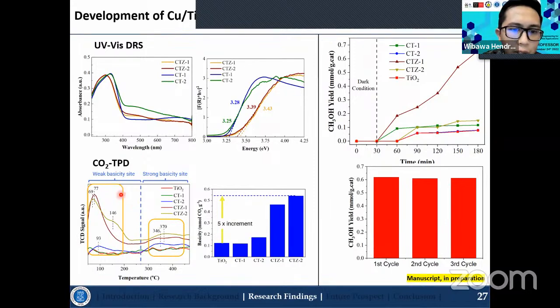So at the low temperature and at the higher temperature, it's indicated as a weak basicity site and also the strong basicity site respectively, for the catalyst. So it can be seen that there is an improvement when we calculate the basicity sites, where the CTZ2 has a 5 times increment compared with the TiO2. So the higher the basicity site can later be beneficial for reducing the CO2 into the specific products.